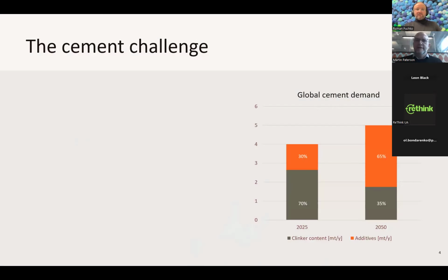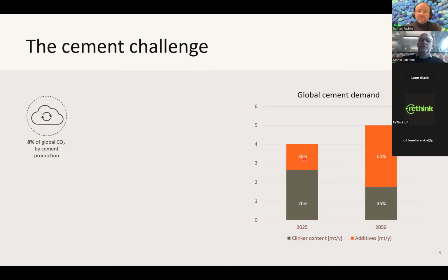A little bit about the cement challenge. I think Leon also talked about it already. We have approximately 8% of the global CO2 coming from cement production. If you look at this graph on the right side, I will try to get a pointer. Currently, the world is producing approximately 4 billion tons of cement per year with a clinker factor of 70%. That means the CO2-emitting part, the clinker, has already been reduced. We're already using additives like gypsum, slag, and fly ash. And moving forward, this is expected to grow.